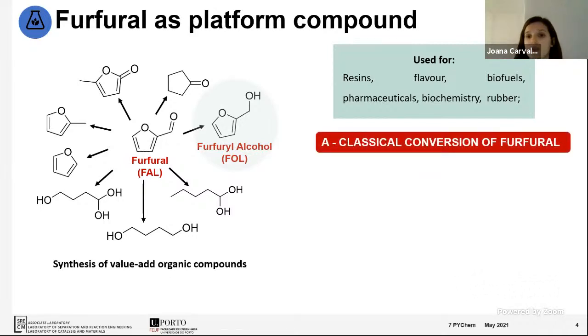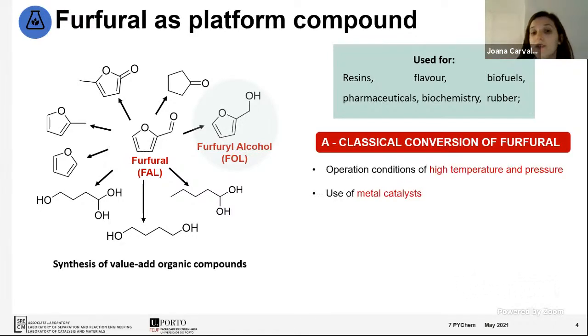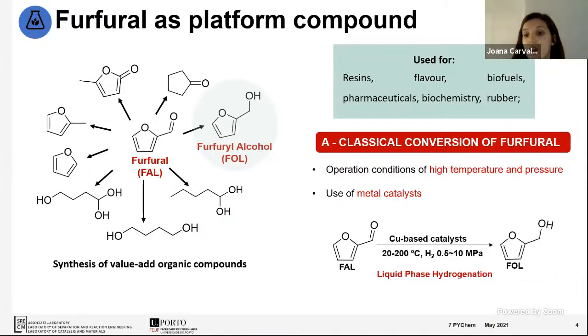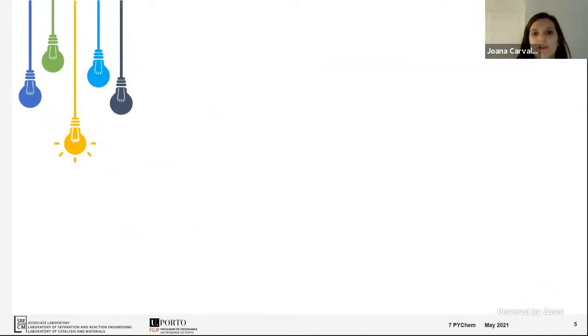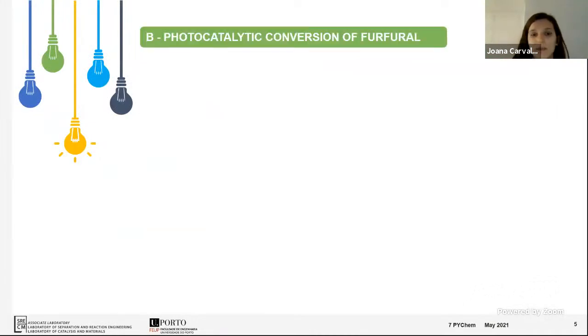However, the industrial process to convert furfural normally requires operating conditions of high temperature, high pressure, and the use of metal catalysts. More specifically, the conversion of furfural using liquid phase hydrogenation to produce furfuryl alcohol involves the use of catalysts based on copper, temperatures around 200 degrees, and hydrogen under high pressure. These reaction conditions are not favorable and not environmentally friendly. For that, it's very important to develop a new alternative route. For that, I talk about photocatalysis.